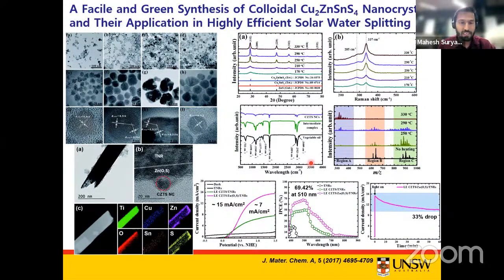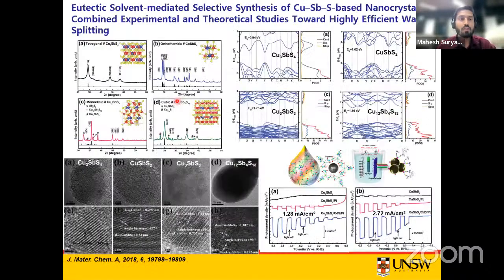Of course, there is no need to explain in detail, but I just want to tell you that the performance of these TiO2 nanorod arrays can be significantly improved by simply doping a non-metal such as sulfur, or by doping visible-light-absorbing compounds such as CZTS, copper antimony sulfides, or CdS or CdSe. Then again, we tried to develop an approach using a deep eutectic solvent as a reaction media to synthesize different phases of copper antimony sulfide. These are again copper chalcogenide compounds, which have a suitable band gap of around 1.3 to about 1.7 electron volt. So what is a deep eutectic solvent?